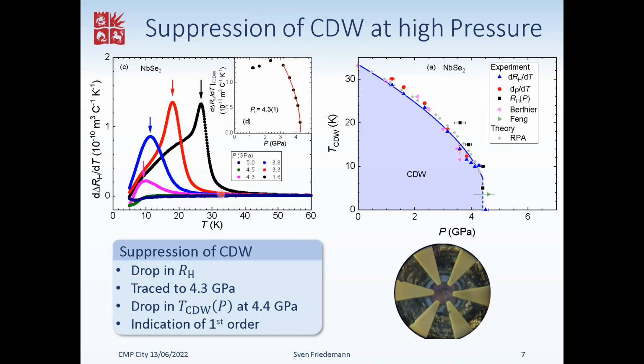There's Hall and electron character to several of those bands, and hence it's a bit more complicated to answer the question, why does it exactly turn negative? But on average, the majority of them is indeed Hall-like. And what is likely is that we introduce a very strong curvature of the reconstructed Fermi surface, and it is these highly curved bits of the Fermi surface that always dominate the Hall coefficient.